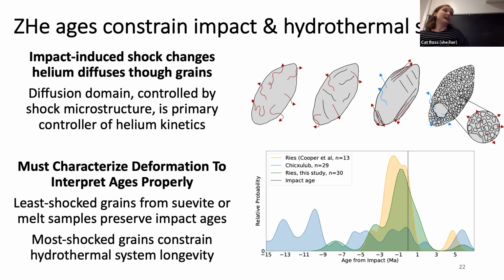So in conclusion, we have impact-induced shock damage that affects how helium diffuses out of the grain, and the diffusion domain is the primary controller of that. So you must characterize your grain's deformation if you want to interpret the ages properly. So if you look at the least shocked grains, then you can potentially get an impact age and date a crater that hasn't been dated before.